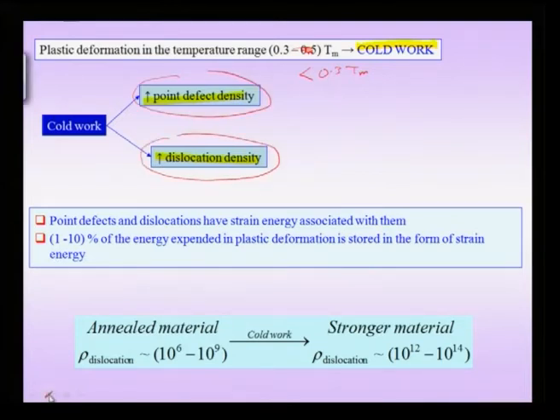So when I am doing cold working, the material becomes a store of energy and the strain energy in the material increases. Typically if you are spending say X amount of energy, about 1 to 10% of this energy expended is stored in the form of strain in the material, and this strain is via the increase in dislocation density and other defects within the material.